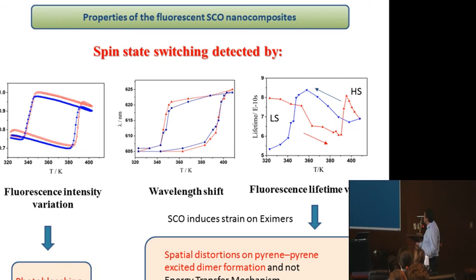So it's better explained by a spatial distortion on the pyrene-pyrene excited dimer formation and not an energy transfer mechanism, because of the distance between these molecules. This was also demonstrated because we do not have a similar effect for the monomers. So this is a good result to confirm this hypothesis.